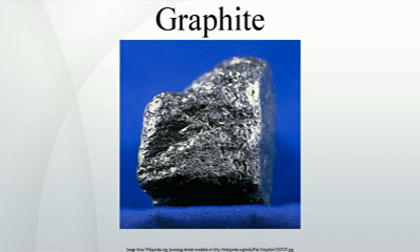The two known forms of graphite, alpha, hexagonal, and beta, rhombohedral, have very similar physical properties, except that the graphene layers stack slightly differently. The hexagonal graphite may be either flat or buckled. The alpha form can be converted to the beta form through mechanical treatment, and the beta form reverts to the alpha form when it is heated above 1300 degrees Celsius.